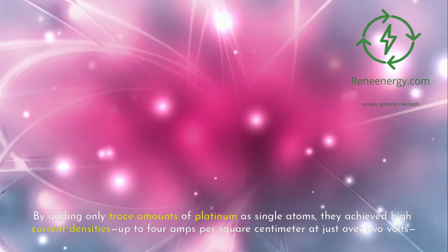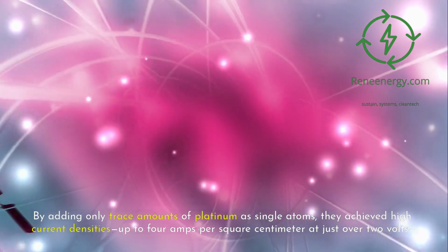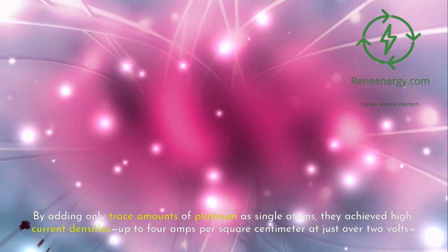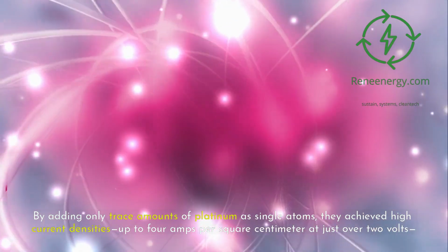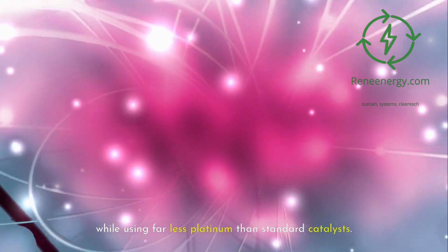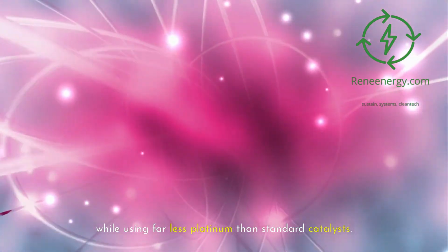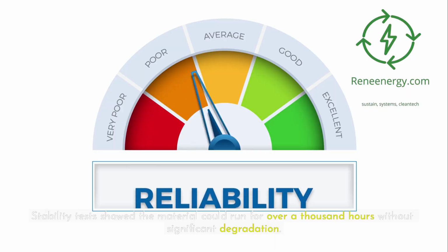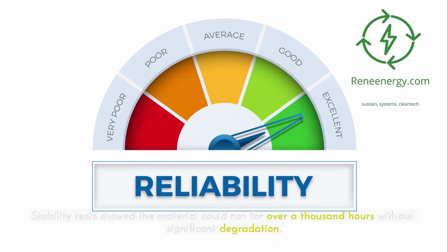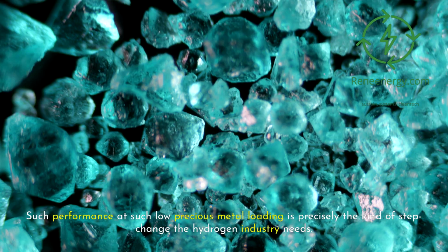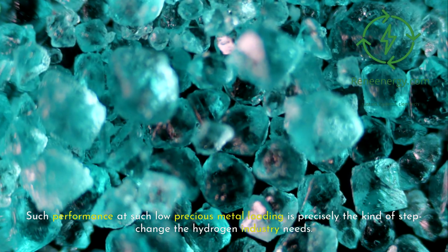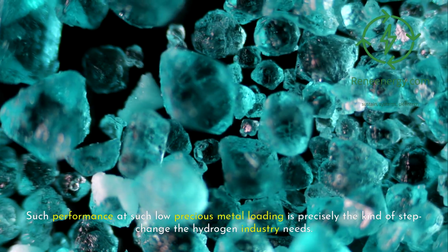By adding only trace amounts of platinum as single atoms, they achieved high current densities, up to 4 amps per square centimeter at just over 2 volts, while using far less platinum than standard catalysts. Stability tests showed the material could run for over 1,000 hours without significant degradation. Such performance at such low precious metal loading is precisely the kind of step change the hydrogen industry needs.